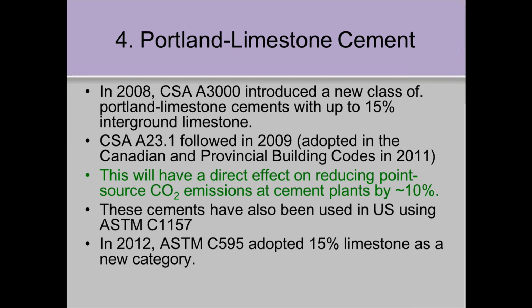In 2008, we introduced a new class of Portland limestone cements. I was actively involved with doing that. It's up to 15% ground limestone, and that was eventually adopted in the concrete standard and eventually in the building codes in Canada. And effectively what that does is gives you the same performance with 10% less CO2 production. So it's a big deal for the cement industry because they potentially face threats of CO2 caps or taxes on their CO2 emissions based on point source emissions. So they've got to reduce their point source emissions. British Columbia already has such legislation in place, and it's costing the industry. So the limestone cements help them get there on top of what they were already doing.